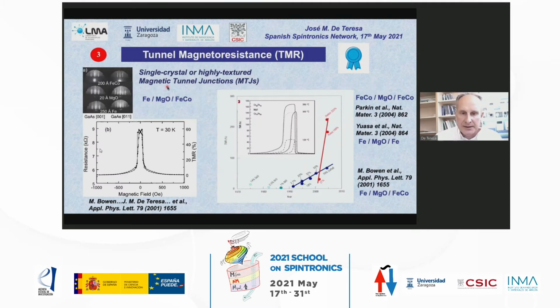And then there was another idea that consisted in preparing these magnetic tunnel junctions in single crystal form or highly textured form. The first samples were based on iron, magnesium oxide and iron cobalt layers. These materials could be grown in situ with a very high crystallinity and a very high texture. In principle, they were single crystals. The first tunnel junctions based on these materials were prepared here in Spain, in the Instituto de Microelectrónica of Madrid, by Alfonso Cebollada and Carlos Martínez Boubeta.